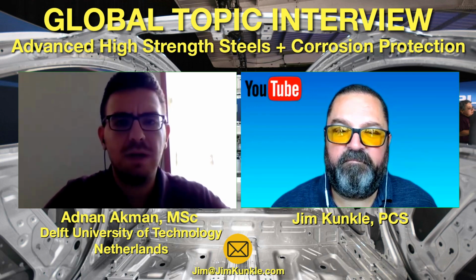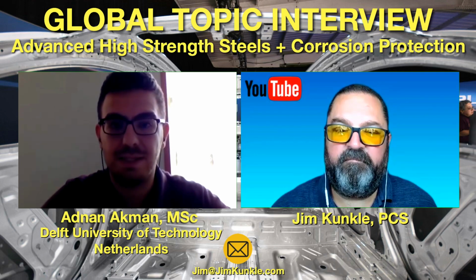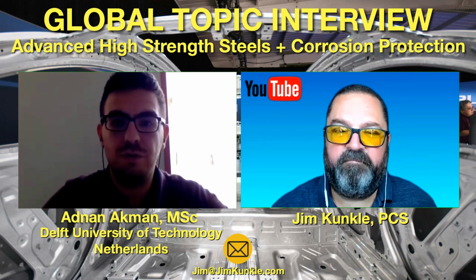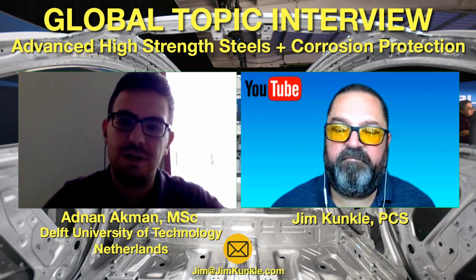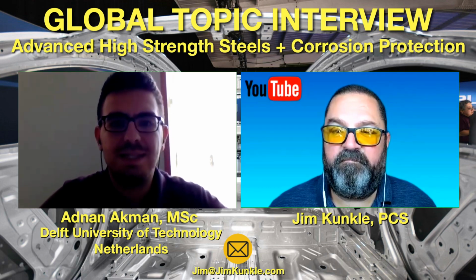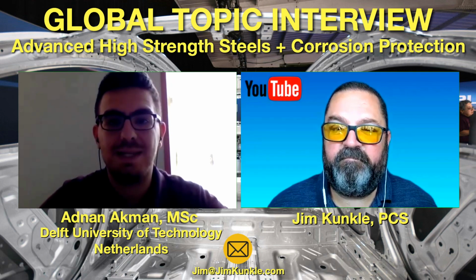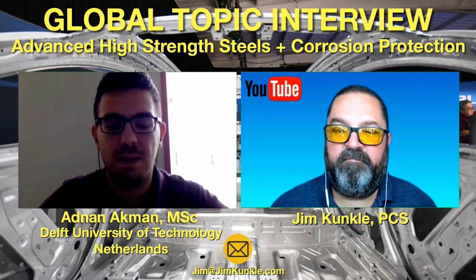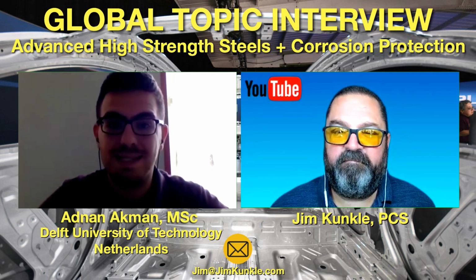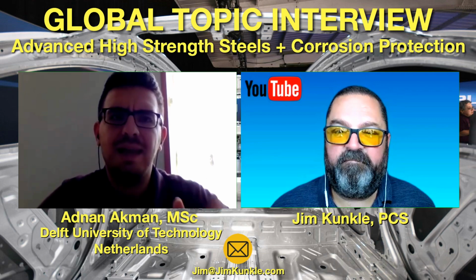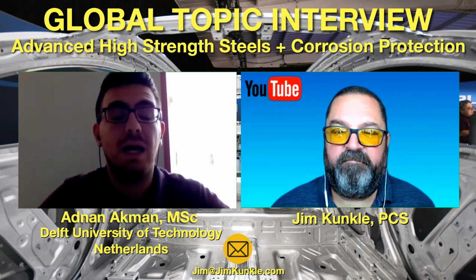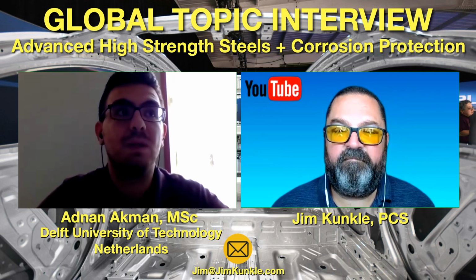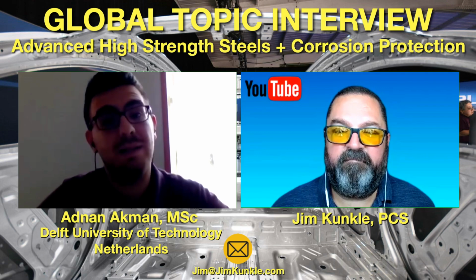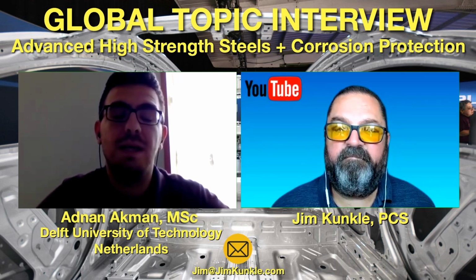So I would like to dive into classification of advanced high strength steels. We can classify these steels into three groups. These are first generation, second generation, and third generation. First generation steels are dual phase steels, transformation induced plasticity steels, or martensite steels, for example. Second generation steels are mostly austenitic, for example, twinning induced plasticity steels. And third generation steels are still in the R&D stage. I mean, engineers are still working on improvement of third generation advanced high strength steels. For example, quenching and partitioning is a quite important steel from third generation advanced high strength steel.